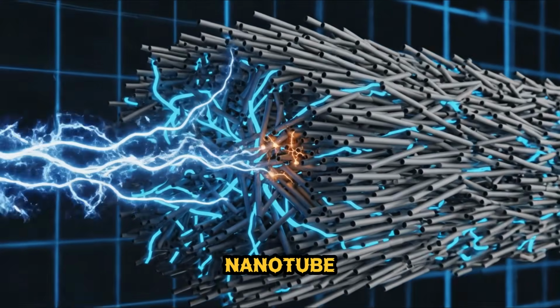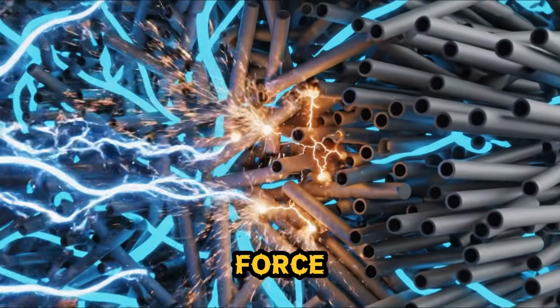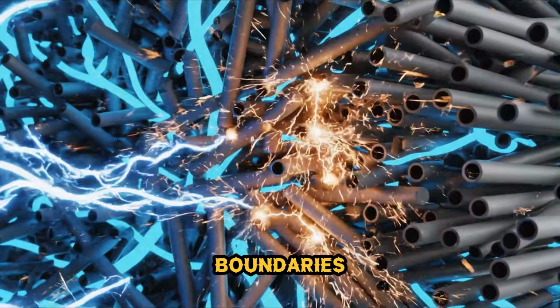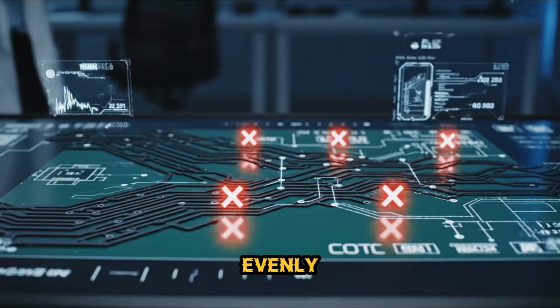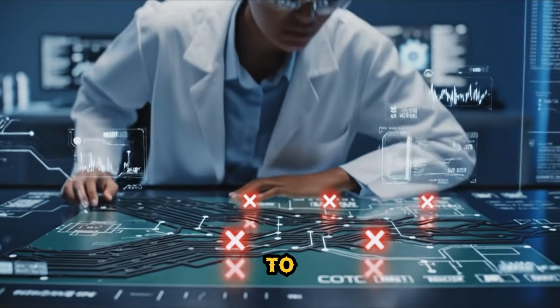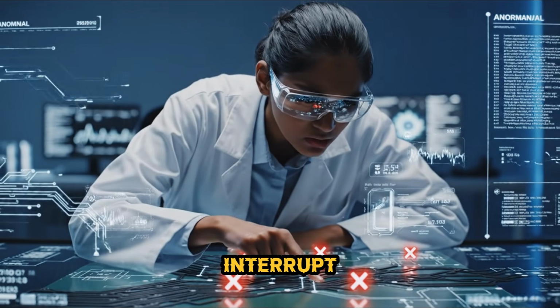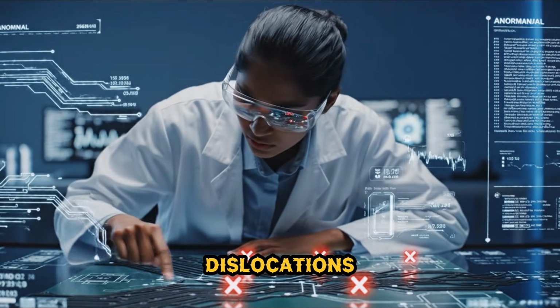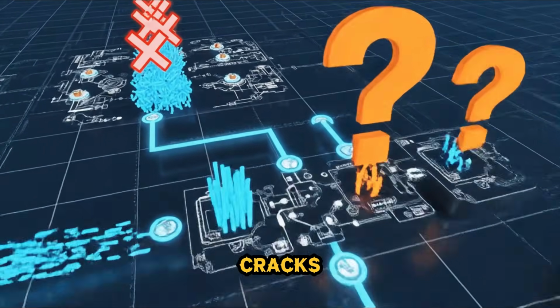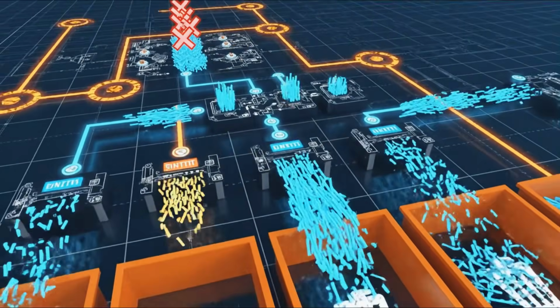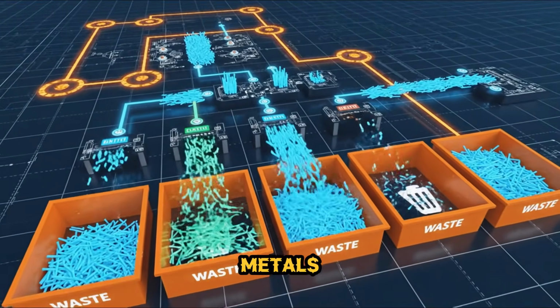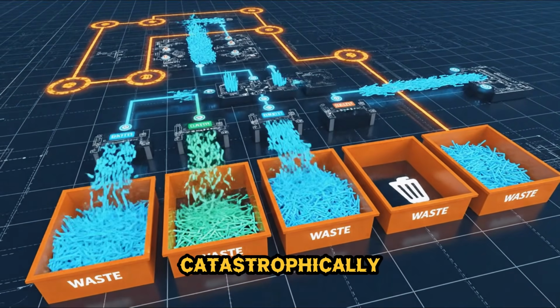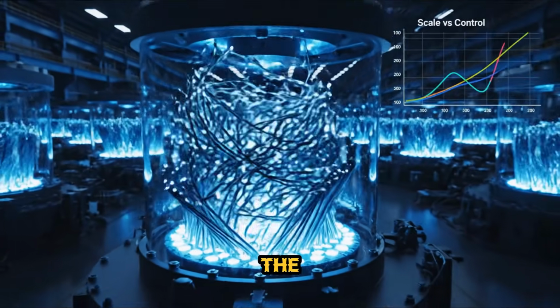In a nanotube, bonds are aligned with the axis of force. There are no grain boundaries. Load is distributed evenly across the lattice. Compare this to steel, where grains interrupt force paths. Dislocations move under stress. Cracks grow unpredictably. Carbon nanotubes don't yield like metals. They hold until they catastrophically fail. Which brings us to the next problem.